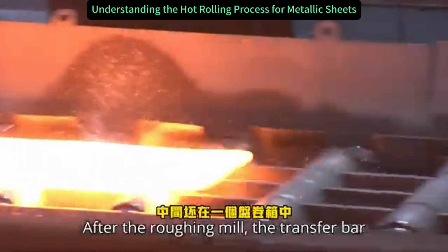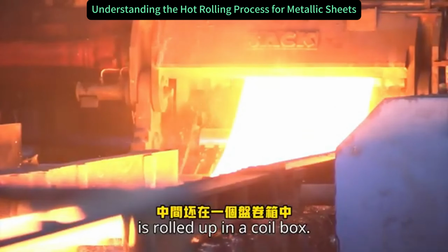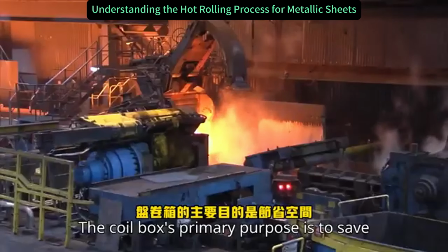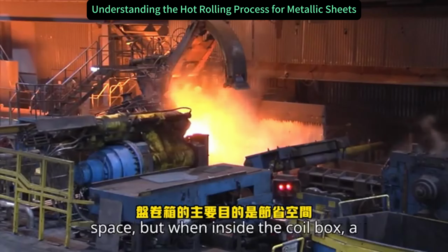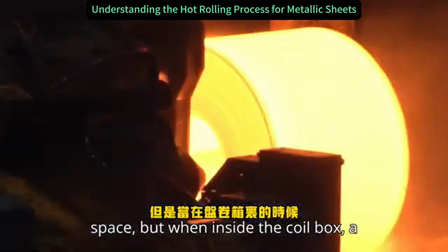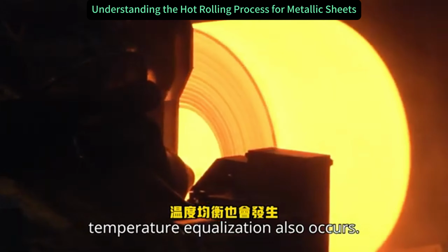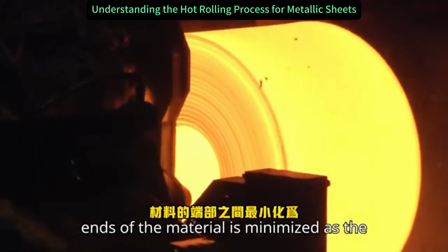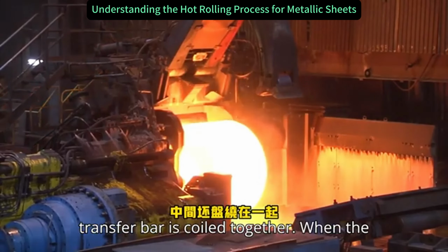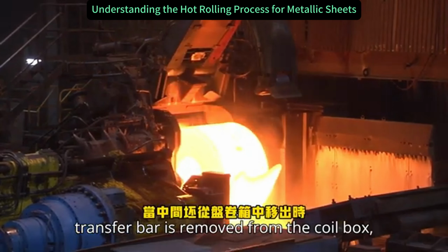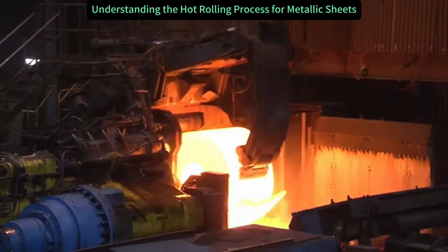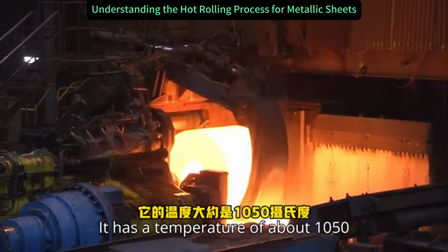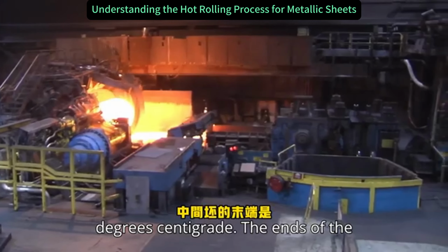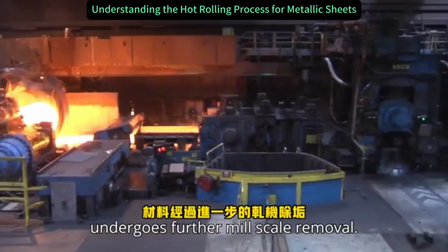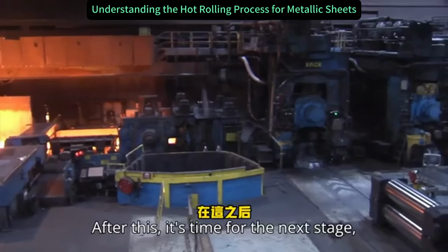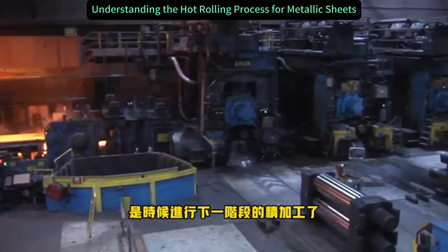After the roughing mill, the transfer bar is rolled up in a coil box. The coil box's primary purpose is to save space, but when inside the coil box, a temperature equalization also occurs. The temperature difference between the ends of the material is minimized as the transfer bar is coiled together. When the transfer bar is removed from the coil box, it has a temperature of about 1050 degrees centigrade. The ends of the transfer bar are cut off and the bar undergoes further mill scale removal. After this, it's time for the next stage, the finishing mill.